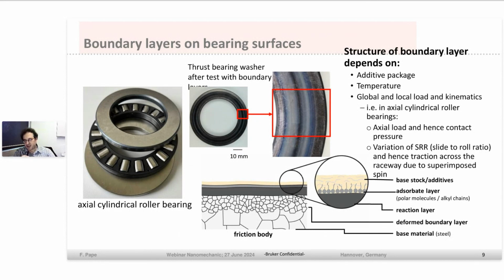And the tribofilm formation depends on the additive package that we use. It can be ZDDP. We can also have some calcium sulfonate and other additives in to improve the anti-wear properties, but also extreme pressure and protection against oxidation of the lubricant. And of course, the temperature influences tribofilm formation and the local load and kinematics. For this kind of axial bearing washers, we have to regard the slip-to-roll ratio in dependence of the position of the roller to the raceway.